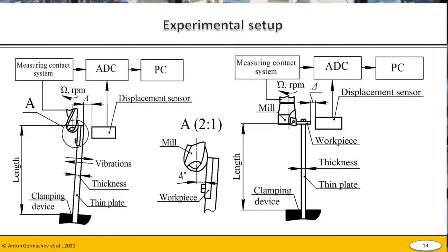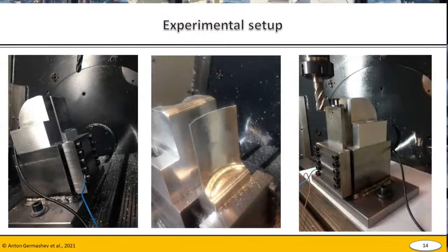Here's the experimental setup. So this is our workbench. We use a displacement sensor, and the least rigid part in our workbench is the thin-walled part. And we determine the behavior of the thin-walled part during the cutting process. Also, we have a special system which measures contact between part and tool. And we are able to determine at what moment the cutting process occurs, and what behavior, what displacement, what movement the part is doing during the cutting process. The next, please. Here is a photo of our experimental setup. The next slide.